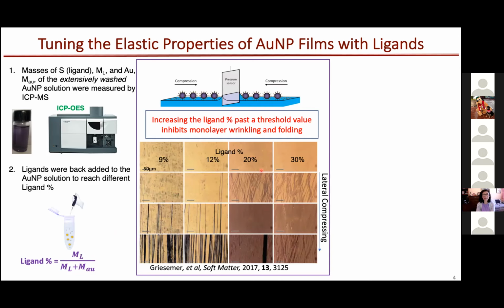When the concentration is about 30% of ligand mass, the wrinkling behavior changes—these films behave more viscoelastic, not purely elastic anymore. So under compression, the wrinkle-and-fold behavior just disappears.